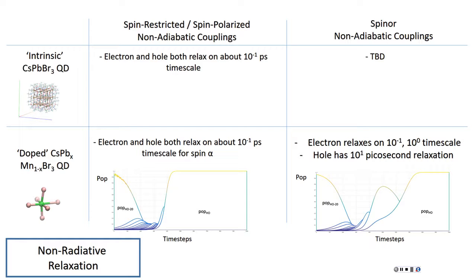But is it legitimate to compare the alpha component and spin orbit? Maybe it reflects the spin flip dynamics, and you need to have both alpha and beta in your spin polarized, and still your spin polarized has no chance for spin flip. So it can be evidence of spin flip transition. So you're saying this state where you have this bump corresponds to the spin flip? Could be. It's not enough data to tell it 100%, but one should suspect it. And spin flip is always slower than all other processes, so it may happen later.